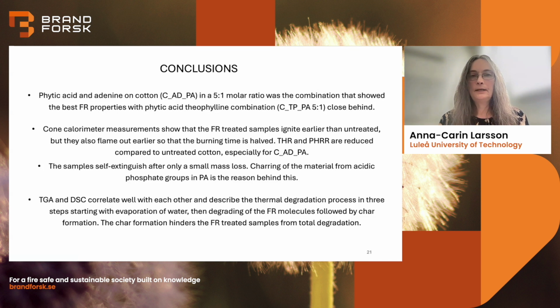TGA and DSC correlate well with each other, so we can describe the thermal degradation process in 3 steps: evaporation of water, degrading of the FR molecules, and char formation. Then the char hinders the samples from degrading further.